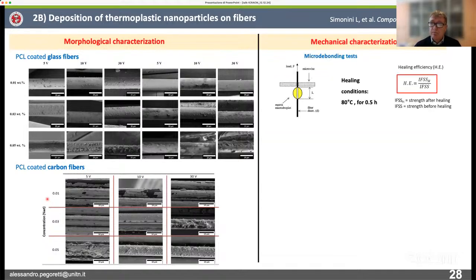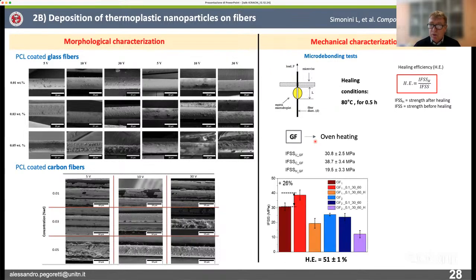At the end, we did measure the initial adhesion, and then after the fiber matrix interface was damaged and broken, we healed basically the material at 80 degrees C for half an hour, and then we tested the adhesion again by using the device I showed you before, which again was used in a collaboration with the University of Tampere in Finland. So in this way, we can measure healing efficiency, which is basically the ratio between the interfacial shear strength in the healed system over the interfacial shear strength in the unbroken system, which is the initial one. Which values we were able to obtain.